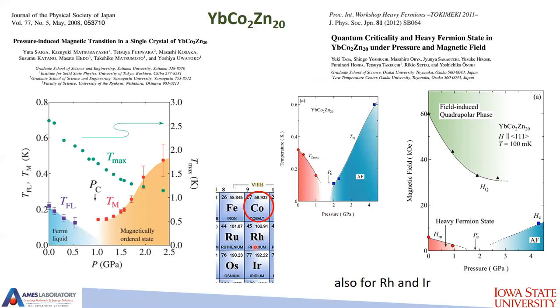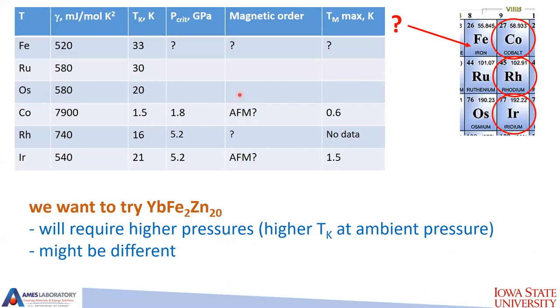This was also done for rhodium and iridium, basically by a subset of the same people, with a similar phase diagram. So literature tells us that for cobalt, rhodium, and iridium, you are able to induce magnetic order. So what happens if we apply pressure for iron? The only thing we know to start with is that we will need higher pressure, since the temperature is higher.